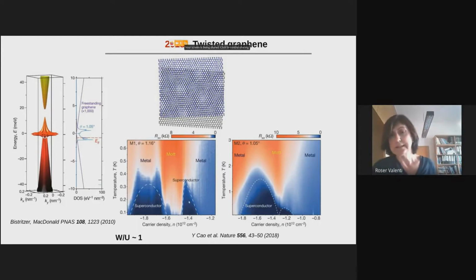And in fact, these are the experiments done in the lab of Pablo Jarillo-Herrero, and this has been confirmed now by many other labs, where they did this experiment of twisting to what is called the magic angle. And here it's shown temperature as a function of carrier density. The way to change the carrier density in these devices is basically by gating the system. And as you see, what they find as a function of carrier density, if we are in the case where there is a neutral carrier, we have a Mott insulator, and by now changing the doping, the system becomes a superconductor. And this was, in fact, an impressive discovery that you can have this physics of correlated systems also in these engineered 2D materials.